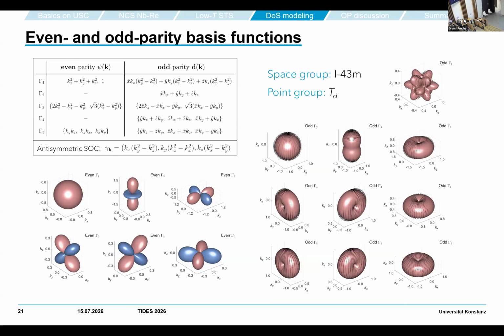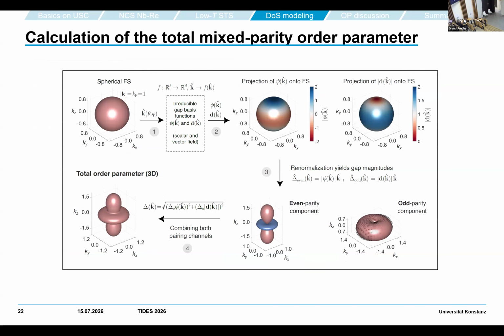And for the odd ones, they have p-wave character, and depending on orientation, all these donut-like parities are still possible. What is shown, and we know this odd component is a vector component, right? This is why you see here all these vectors. So this is a representation of the vectorial component. Okay, so this is the input that we have, and then we have to calculate what we would expect for the order parameter. And so this is cartooned in this image here.